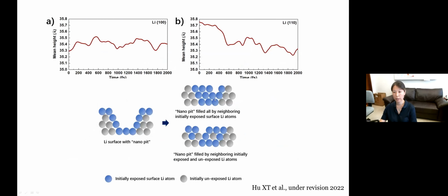So a quantitative result to describe this process is shown here. This is to tell that on the surface of the lithium, when a pit or surface roughness is created, the neighboring surface atoms of lithium, or even the bulk ones, may diffuse into the pit or the roughness to fill it out, so as to remove the roughness of the surface, right?